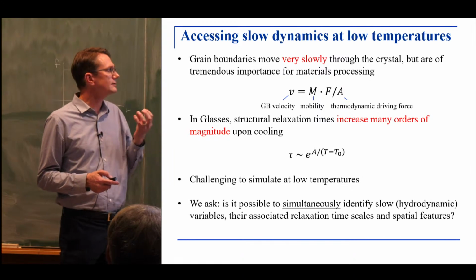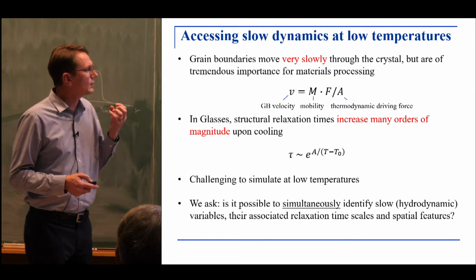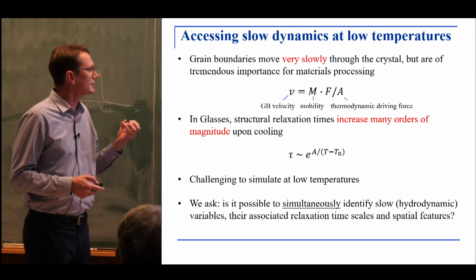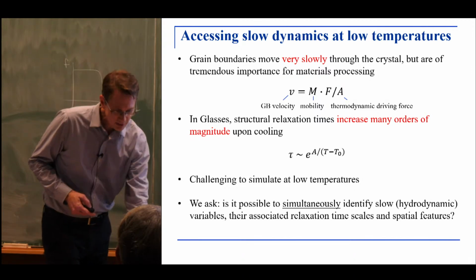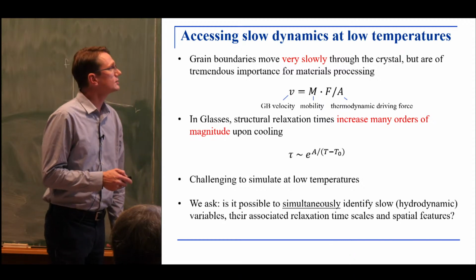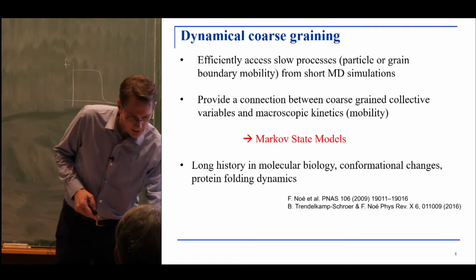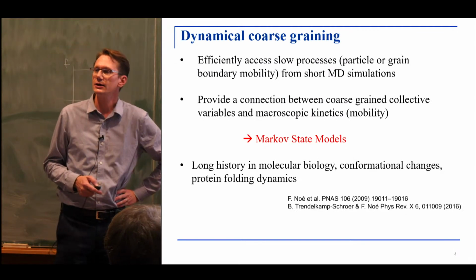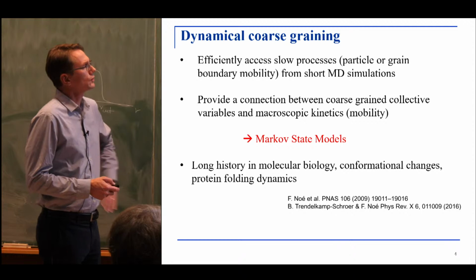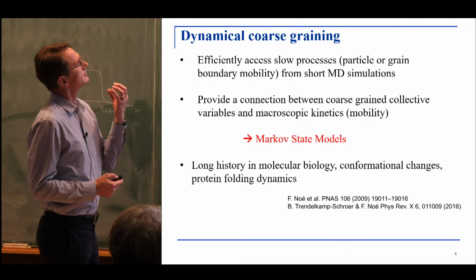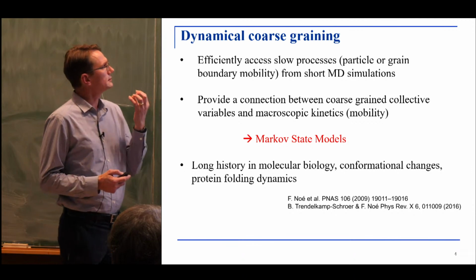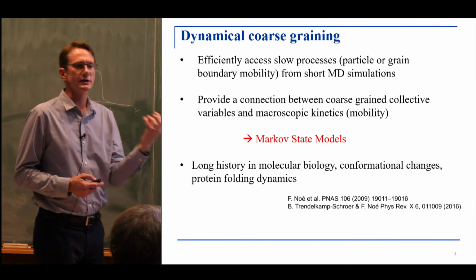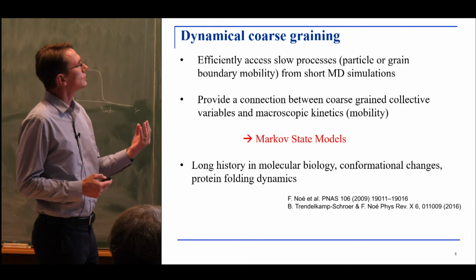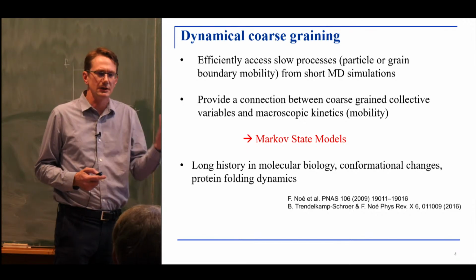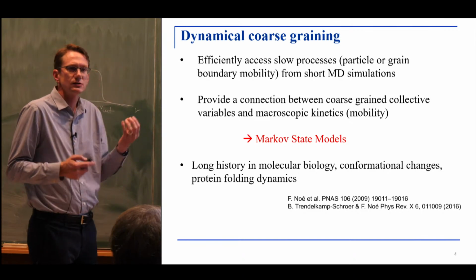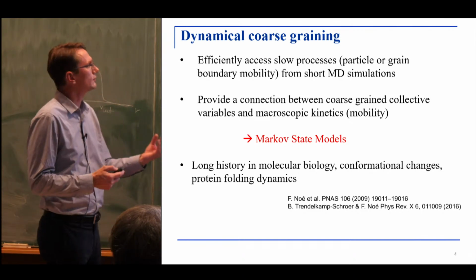I mean, the softness method is very nice. It obviously finds structural features, but not directly information about the relaxation time scale. So in doing so, can this also help us with this slow time scale problem? In some sense, what I would like to do is a dynamical coarse graining. So simplify the system, try to come up with a method that accesses the slow processes from short simulations, and in doing so, provide a connection between some coarse-grained collective variables and the macroscopic kinetics, which is the mobility of the particles or of the grain boundaries.